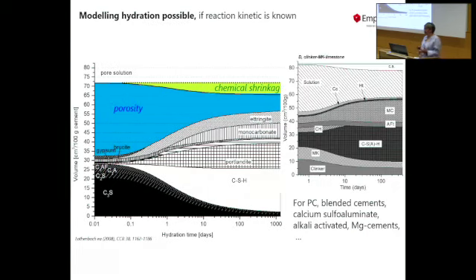One can do the same kind of modeling, obviously not only for Portland cement, but also for any kind of blended cement. There, normally the big problem is to figure out how much of your metakaolin or fly ash or slag really reacts. And this is the thing we cannot predict. You can look in literature and find some general rules, but it's not so easy to figure that out. And that's also why we need, for instance, the R3 test, where you can see a bit the reactivity of your cement.